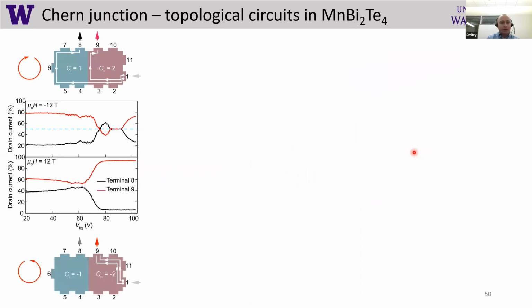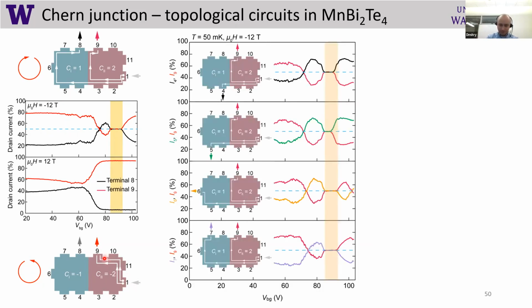So we now realized this situation which I described in this yellow diagram. And we also did more measurements. For example, we reversed the winding of the chiral edge state from clockwise to counterclockwise. So now all current goes from 1 and gets to 9, as you can see here. It's pretty flat, roughly 95% going from terminal 1 to terminal 9, again just following the edge states. Another aspect of this, as I described, is the independence of length. So now we can take this geometry and change electrodes. We can take electrodes 4, 5, 6, 7, 8, and demonstrate that with small variations, this current splitting is exactly 50-50 in all these device configurations, independent of the length again.